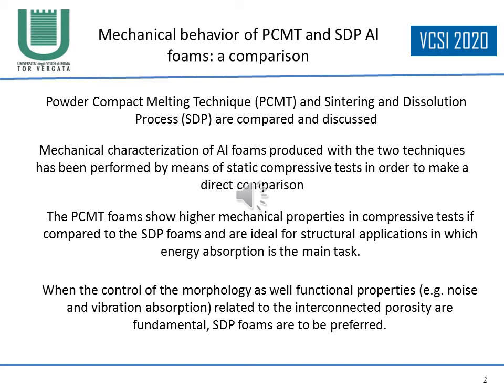PCMT foams show higher mechanical properties in compressive tests compared to SDP foams and are ideal for structural applications in which energy absorption is the main task. When control of morphology as well as functional properties — noise, vibration, and absorption — related to the interconnected porosity are fundamental, SDP foams are to be preferred.